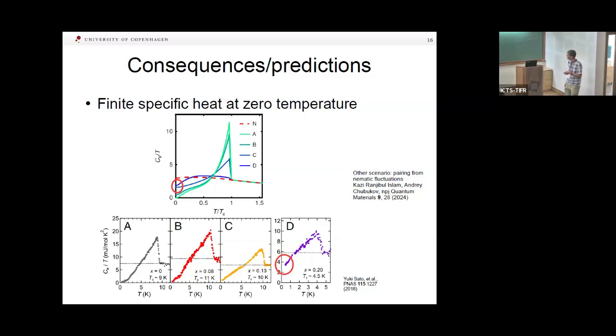And exactly this is also measured on the iron selenium sulfur compound. So again, for a small doping, 0, 0.08, 0.13, the specific heat goes to zero at zero temperature. But for 0.20, which is beyond the transition into the ultranodal state, it seems that there is a finite specific heat if you extrapolate to zero temperature. Again, a signature of a possible Bogolubov Fermi surface.